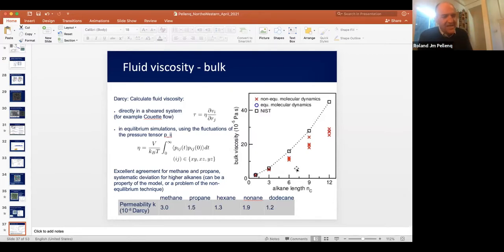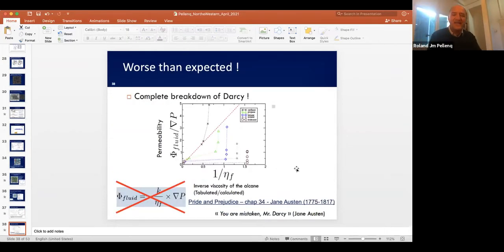And as I said, permeability is actually a property of the material itself. It should not depend on the type of molecules in the pores, nor the amount of those molecules in the pore. So let's try to plot K as a function of a reduced quantity, which is this 1 over eta. So we have this flux divided by the pressure gradient, and that should be equal to K over eta. So we plot as a function of eta, and we should have K as a constant. And as we can see, this is not at all a constant. It not only depends on the type of fluid, it's different from methane to dodecane, but it also depends on the amount of fluid you put in the pore. So Darcy's equation is actually not valid at the nanoscale.